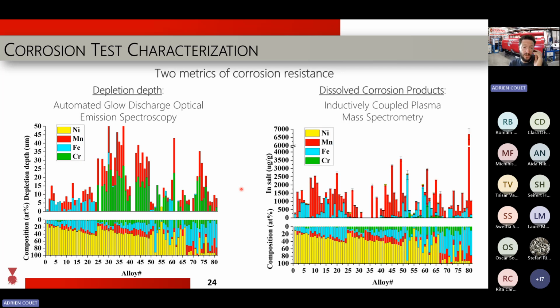So we decided to do the opposite: we use the ICP-MS of the salt to look at the corrosion products in the salt. And this is more of a holistic, general corrosion quantity that you can work with. And you see how you have all the ppm of elements in the salt for all those. This is about 82 tests. And those tests are the ones we've used for training the machine learning algorithm, which I'm going to talk about right there.